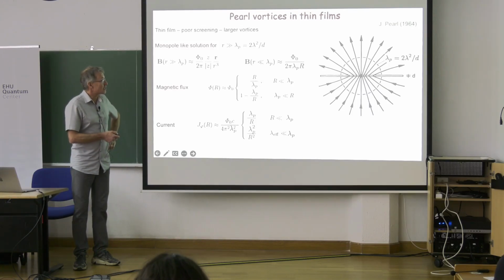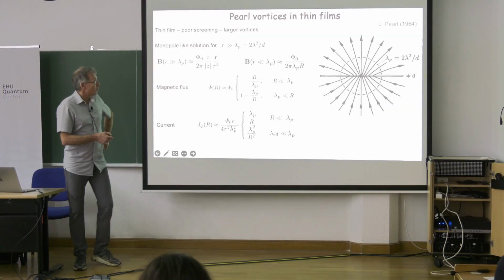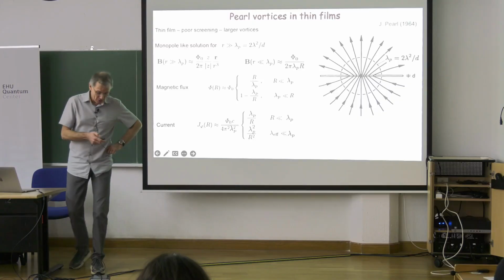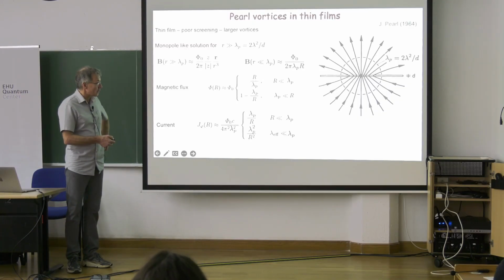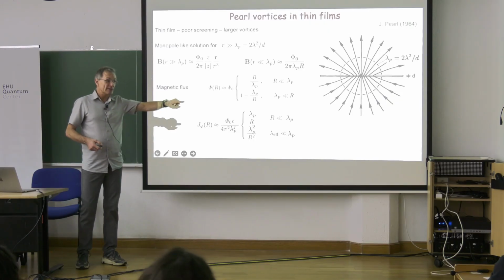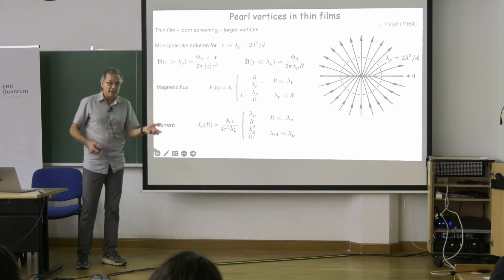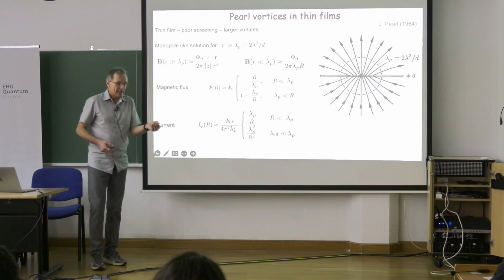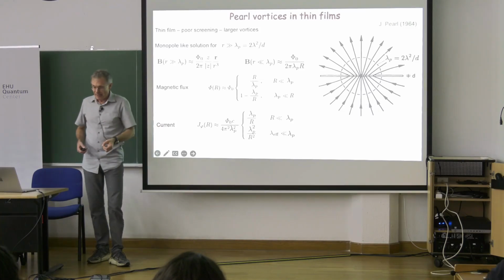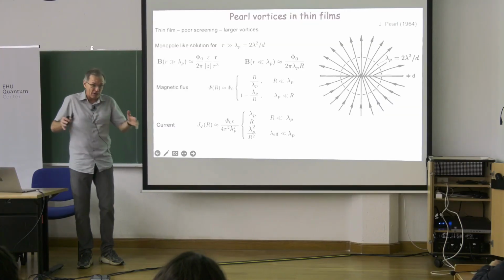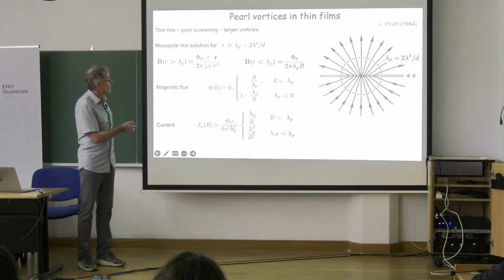superconductor? This was studied half a century before this by Mr. Pearl, who looked at how a vortex looks in a thin film of thickness d. He figured out that if you have a thin film, then the current that flows there will produce very little magnetic field, because current density can be large, but total current is small, so it's very difficult to screen magnetic field. That's why the effective screening length is called the Pearl length. It's not London lambda, but lambda multiplied by another lambda over d factor, so it's much larger.